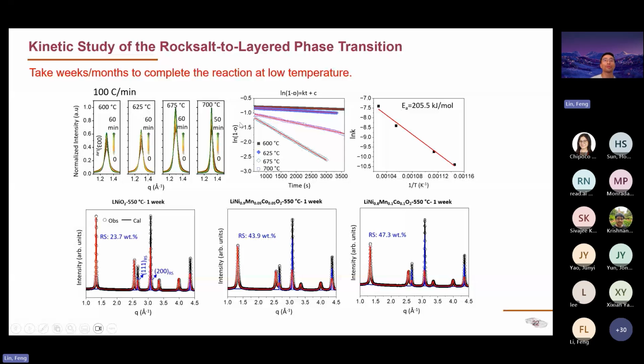So let's look into the method that we could use, for example, the traditional method. With the traditional method, we did kinetic studies at 600, 625, 675, and 700 degrees C, and we can monitor the kinetics of growth for different materials. So for example, here we have lithium nickel oxide calcined at 550 degrees C, which is a temperature 200 degrees C lower than the traditional temperature, and the same thing here with 90% nickel, and here with 80% nickel. After 1 week, we still get a rock salt percentage of around 24% in the lithium nickel oxide case,